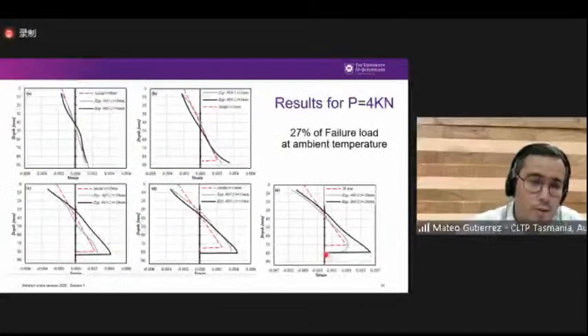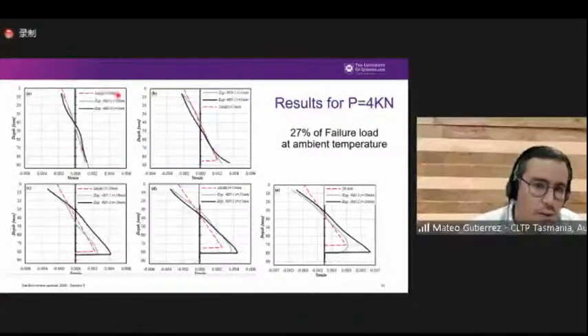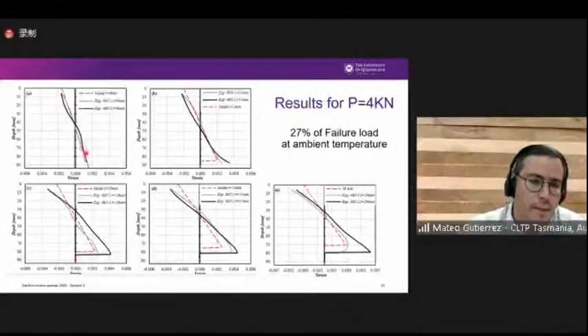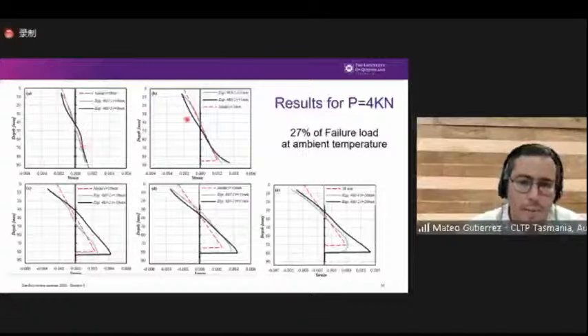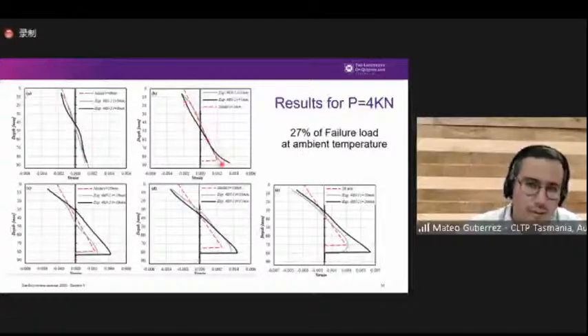We reproduced this model. So what you can see here in grayscale is the strain profiles in the beam, and the red dashed line will show the model that is predicting the behavior. As you can see here at ambient temperature, this is time zero of exposure. The model basically matches the performance perfectly. Then after 5 minutes of exposure, it still represents pretty well the behavior of the beam and so on. So you can see here the results of 10 minutes, again, experimental results against the model, 15 minutes and 20 minutes, basically until reaching the failure.